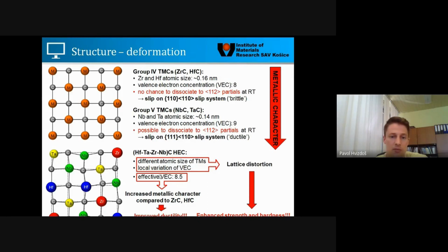However, at the same time, we have an effective valence electron concentration due to the equal portion of group 4 and group 5 transition metals which took part in building the structure. So we have an effective valence electron concentration of 8.5, which is slightly higher than the 8 of group 4 transition metals. So it means that we have a slightly increased metallic character compared to the zirconium carbide and hafnium carbide monocarbides, which means that we can expect improved ductility, and this is also what we could prove. So this is something which is completely new, and at the same time very interesting,